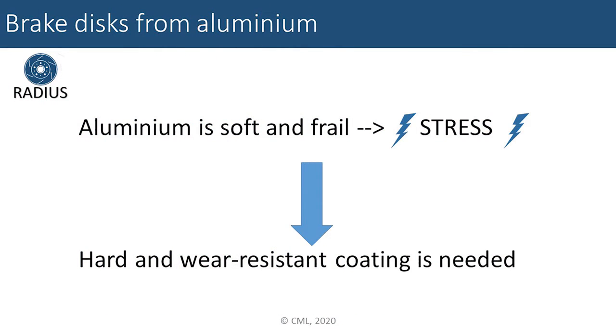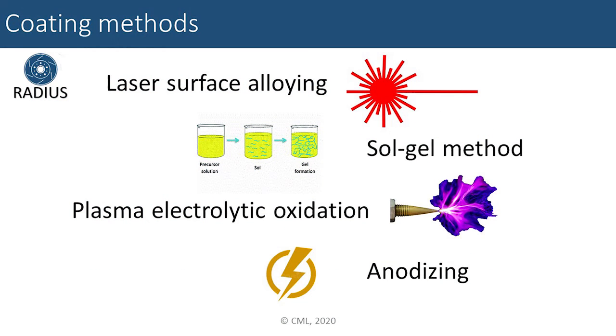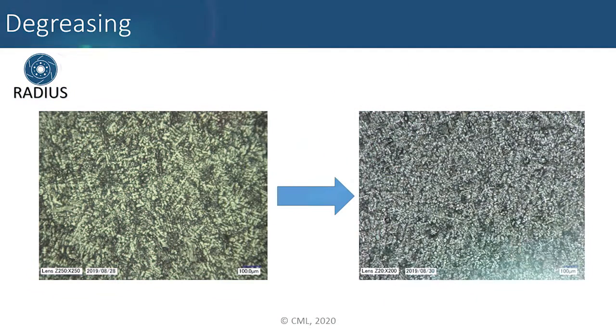The main problem with aluminium and its alloys is that they are too soft and frail to be used as a long-term brake. They wouldn't endure the increased stress. The solution for this problem can be to develop a hard, wear-resistant coating on the metal base. We tried 4 different methods on the test samples: laser surface alloying, sol gel method, plasma electrolytic oxidation, and anodizing.